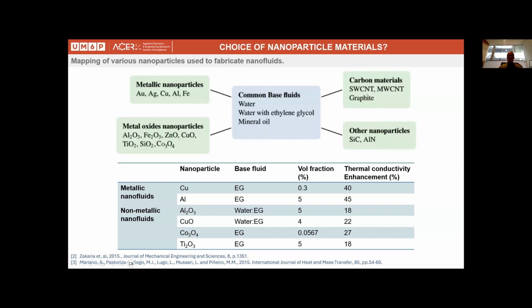So I wish in the future that we can be able to create this type of carbon-based materials or allotropes of carbon in a cost-effective way, so we can create nanofluid with even higher heat transfer or thermal properties. One can think about oxides and so on. This is just a small table here showing you that metallic particles have higher thermal conductivity if injected into some base fluid like ethylene glycol at a volume fraction of, let's say, 0.3, an enhancement of 40% we can achieve. With aluminium, we can achieve even further, 45.